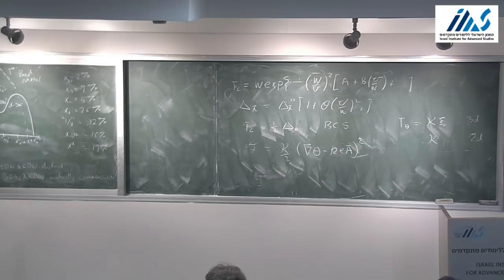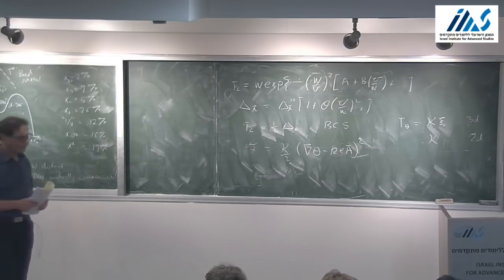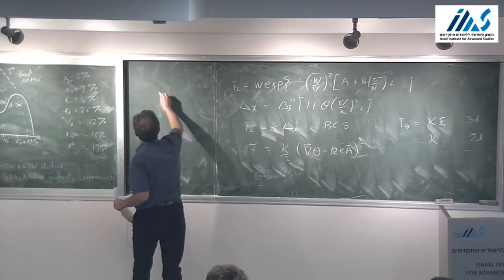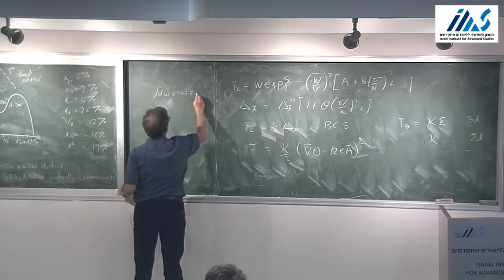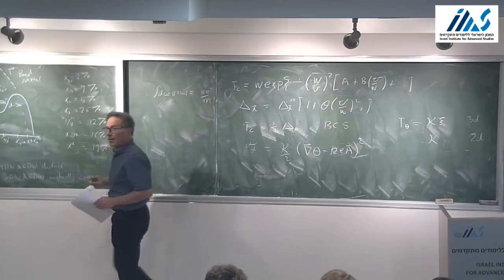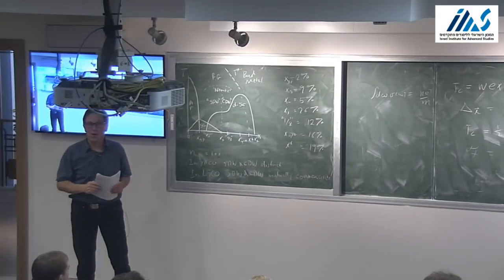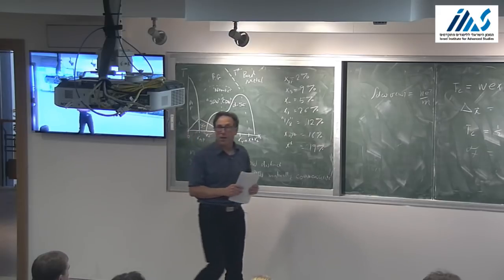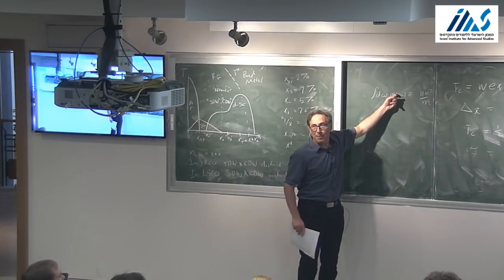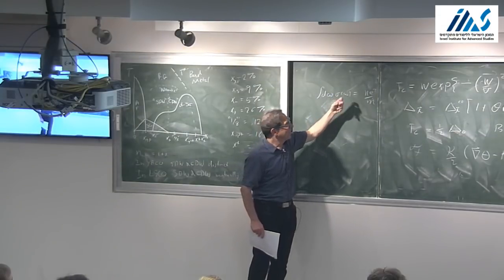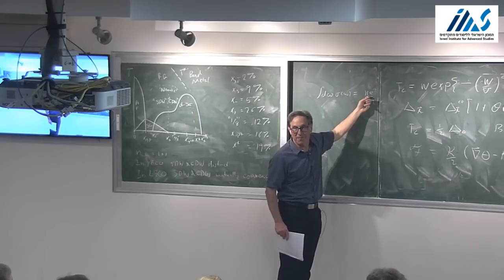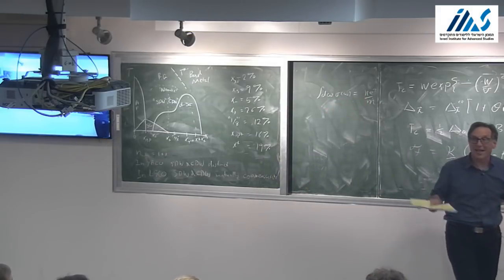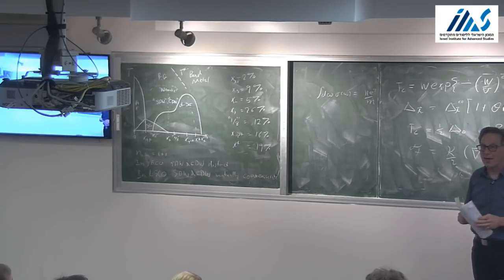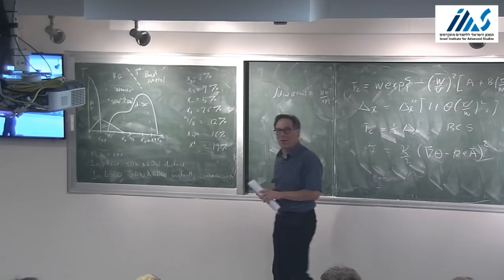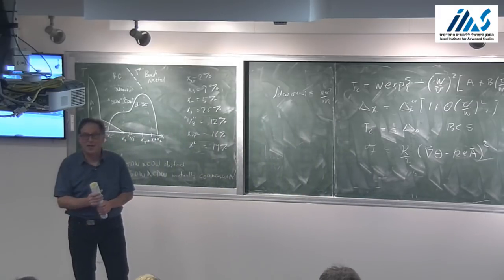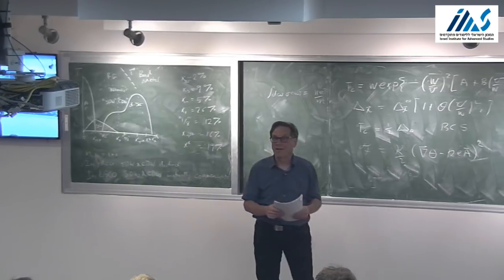Yeah, so it's easy to understand why it's so large in conventional superconductors. In any superconductor, I have the F sum rule. So the integral of the conductivity is Ne squared over m. In a clean superconductor, all of this weight collapses into the superconducting delta function. So kappa is Ne squared over m. Okay, that's all electronic energies that has nothing to do with the small scales of superconductivity. Now, in dirty superconductors, this can be reduced, but you start with it so big compared to Tc that you just never get anywhere near here.